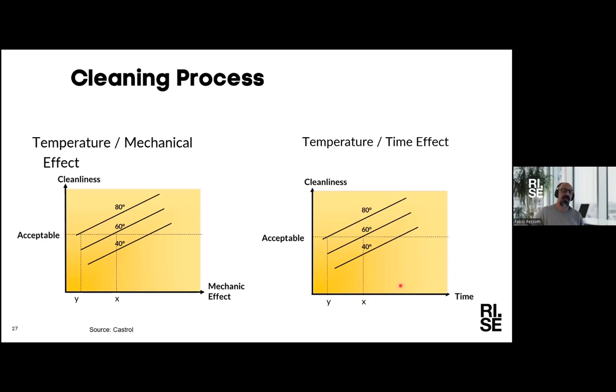And as I said, also these 4 types of stages need to be correlated. So there are correlations between the temperature and the mechanical effect, and one should find where you can put your process parameters in order to have the best or the most acceptable cleanliness. And the same runs for temperature and time effect. Depending on how much time or how less time you have on the process, you can have a more acceptable cleanliness.